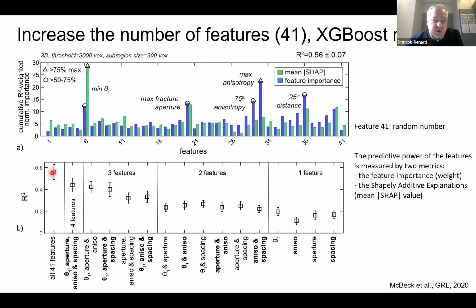Now, if we put all the 41 features, we have an R square of 0.56. But what we can do also is select some features. If we select the 4 features that have the most importance, that's the angle of the fracture, the opening, the spacing between fractures, and the anisotropy, so it's not very far from the elongation in this case. On average, we have an R square of 0.44.